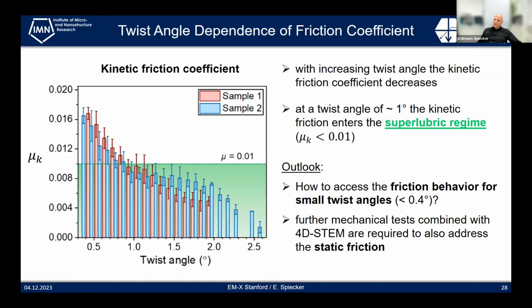But of course, we did not evaluate the very last slip motion because then the overlapping area is too small and maybe already some edge effects set in. So of course, the larger the overlap area, the less important is the edge, which always makes an additional effect, at least is expected to make.